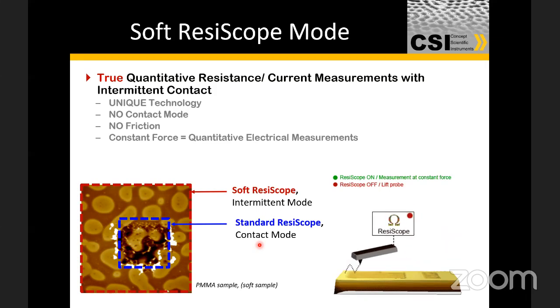and tapping or non-contact mode of the AFM, where if you have soft surfaces with high surface energies where the tip tends to stick, we have to resort to not making a continuous contact to measure the current, but we have to make intermittent contacts. As you can see in the inset image here, using the classical technique and using this intermittent contact technique, we are able to get much better electrical resolution on the sample. And this is, as I said, an extension of the Resiscope technique, where we're not making a constant contact, but hovering over the surface and making intermittent contacts and making the measurements at those time steps.